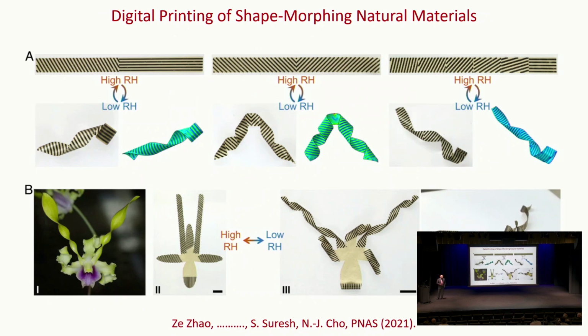So one of the toughest things to create digitally is the orchid, which is the national flower of Singapore. So we decided to create an orchid. How do you create an orchid, and how do you create folds and curls? On the top you have two different patterns that are joined together, and in a single strip you can print two different patterns in different orientations. So if you change the humidity from low humidity, say 30, 40%, to 75% humidity, it will curl differently, and it's shown here. In the middle, you have the same strip at different angles, and you see how that curls.